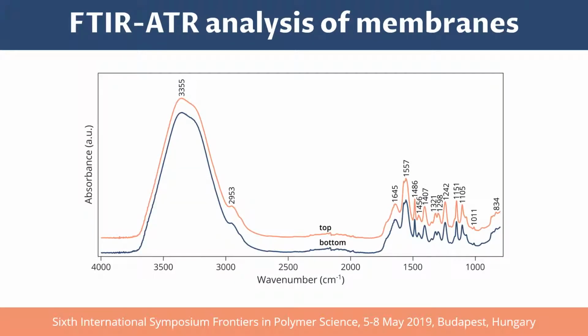We started with the characterization of chemical composition using FTIR-ATR technique. In the case of membranes, different wet surfaces have almost identical composition, indicating good symmetry. Bands corresponding to the formation of polyacrylic acid are evident in the spectrum, while the characteristic bands of polyether sulfone as the hydrophobic matrix also appear. We observed no significant shifts in the bands, which indicates mainly physical blending of separated phases.